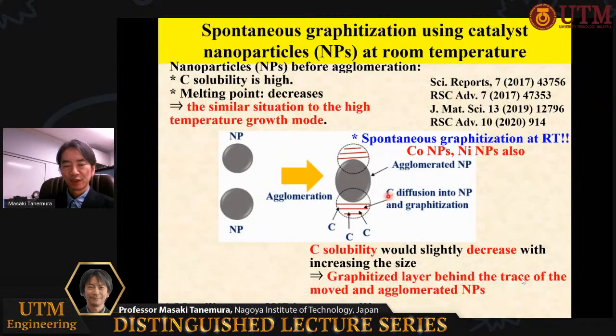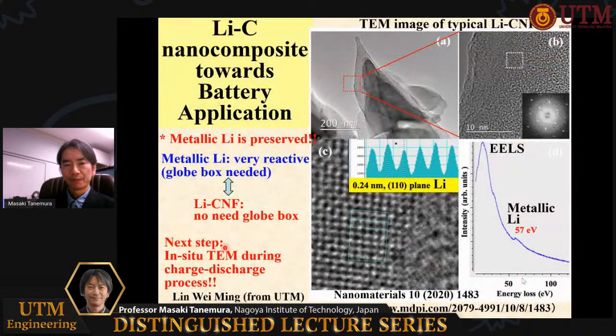Another important point is the metallic state of the nanoparticle. Usually, a nanoparticle is very reactive and is easily oxidized. But in this nanoparticle-dispersed carbon system, the metallic state of the nanoparticles is preserved. Encouraged by this fact, we tried a lithium-carbon combination.